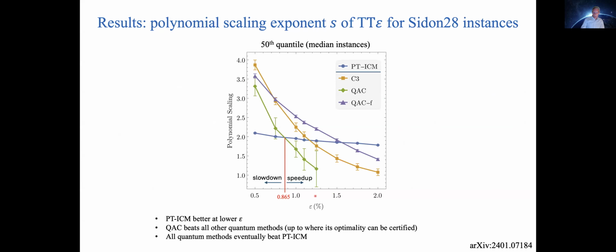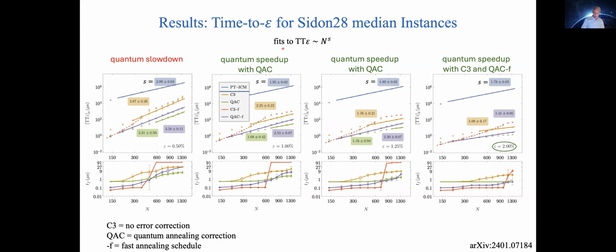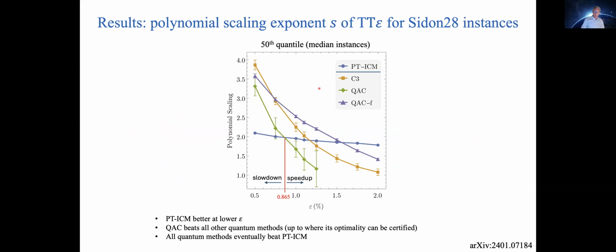And if we put it all together, we did many more experiments for different optimality gap values. So here is now the slope, the polynomial scaling. So this exponent s, this is all being fit to the function n to the power s. So these are all polynomial. They're not exponential because we're doing approximate optimization. So we're interested in this scaling exponent s, the slope on these plots. And what you're seeing here is a summary of these results for different values of epsilon.